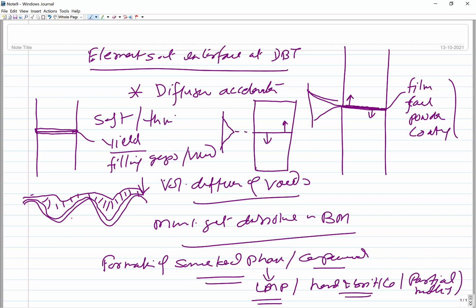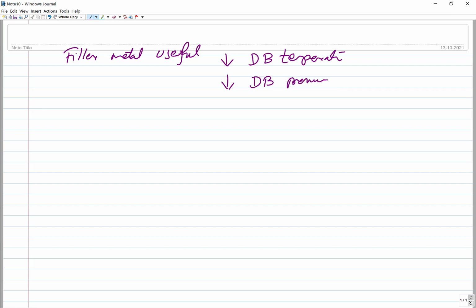And considering these aspects, if we choose the diffusion accelerators or films and foils to be used for the diffusion bonding, these can be extremely useful. So when the filler metal is selected appropriately, it can be useful in a number of ways, because it helps in lowering the diffusion bonding temperature. So this is good if you can realize the diffusion bond at the lower temperature. It reduces the diffusion bonding pressure. So this is also good. For a given press size, you can develop the diffusion bond of larger size components. It also reduces the diffusion bonding time. So all these three things are favorable.